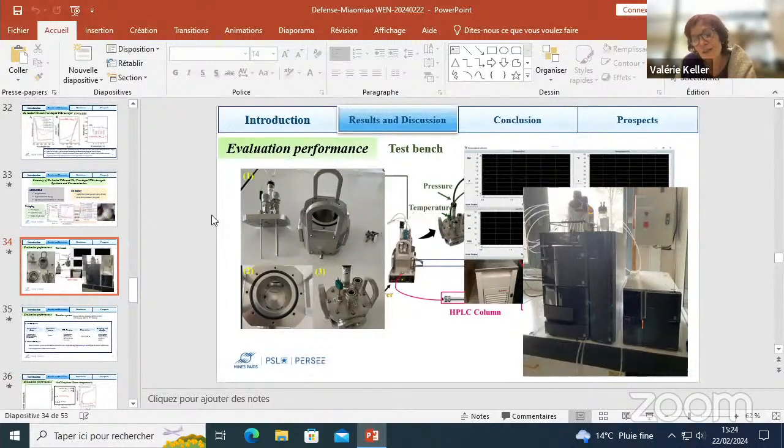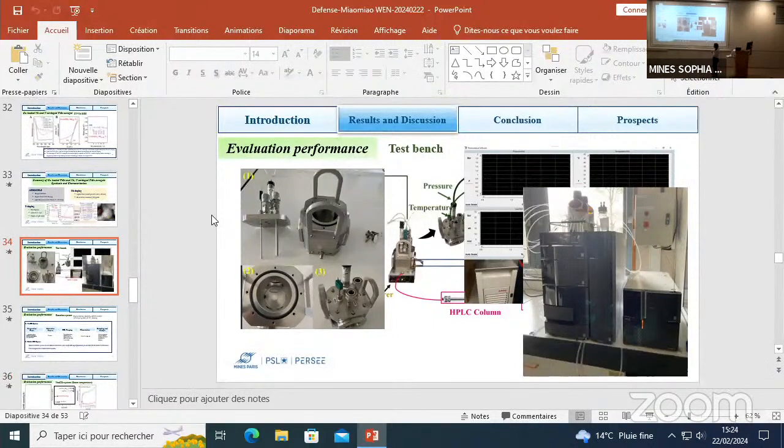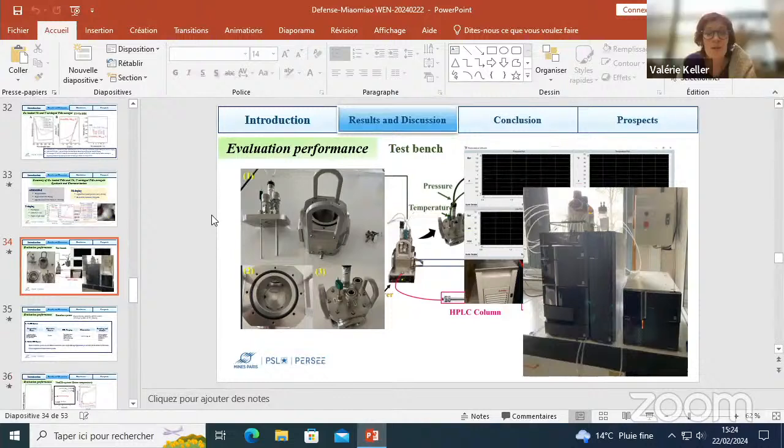And actually just some carbon residues on the surface of your catalyst may be enough to produce methanol or other carbon-based compounds. So you have to check this blank experiment also. Yes. Okay.